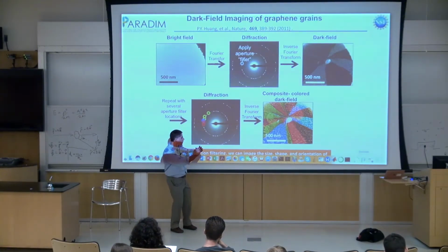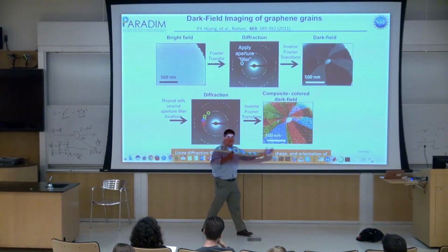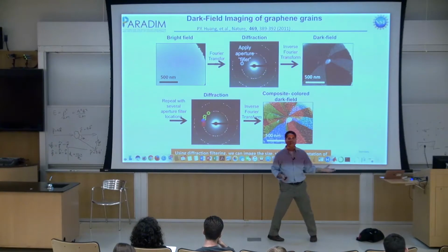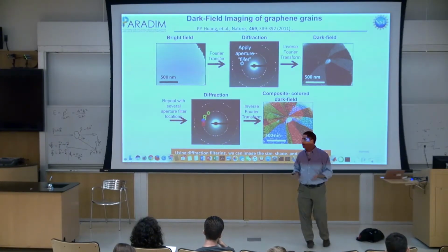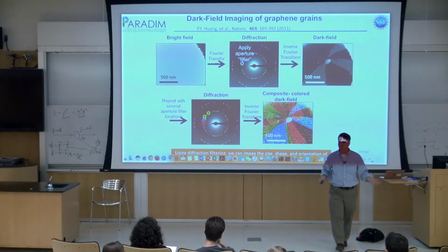Physically, what's happening is my probe in real space is getting fatter and fatter and fatter. And that is just delta k, delta x is a constant. That's your uncertainty principle. If I want to have very, very good momentum resolution, I have to have bad spatial resolution.